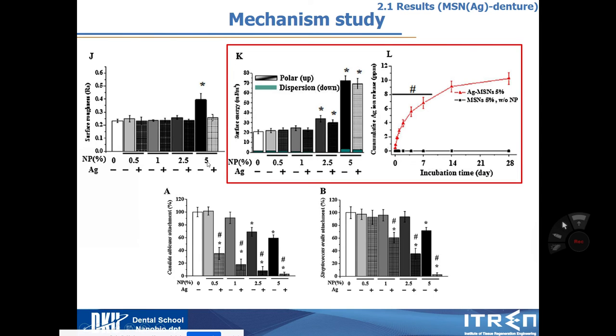And then I want to know what the mechanism is. The surface roughness is higher without silver and in 5% increase, but mostly they are similar with or without nanoparticle incorporation. The different thing is the surface energy from the hydrophilicity. So with or without silver, when you incorporate nanoparticle, they will show more surface energy, which is more hydrophilicity. So we can expect that this hydrophilicity can be one mechanism to reduce biofilm or bacterial attachment formation. And then absolutely, little silver ion from the denture can show some inhibitory effect. We can expect that.